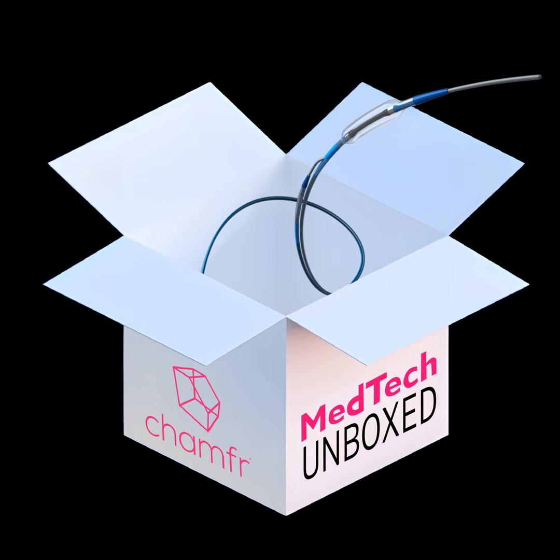You have that additional redundancy, but I'll actually compare this to something I learned with leads. A lot of leads like to use multi-filar coils, and there's a theory out there that if one of the filars breaks, then at least you still have your others. But in reality, if one filar breaks, all of a sudden you have a weak spot in your coil, and it's not going to be very long before the rest of your coil breaks in that same location. And so if you have a defect in your multi-layer balloon, yes, you have additional layers, but if it creates a failure point, it's still going to fail at that defect. Gotcha.